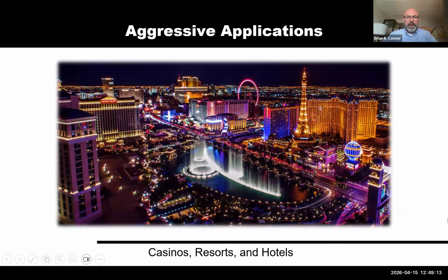Another application where you're getting really aggressive installations is casinos, resorts, and hotels, because of, again, low flow fixtures, cleaning chemicals, and maintenance personnel flushing these chemicals down the drain without flushing with water behind, plus the soda fountains and bar sinks that have really acidic fluids flowing into them. So what we would recommend is using maybe an enhanced coated fitting or two, a P-trap, and a couple of lengths of pipe until downstream, where more water is introduced into the system to flush that down and dilute it. And then you can switch right back to your standard iron.